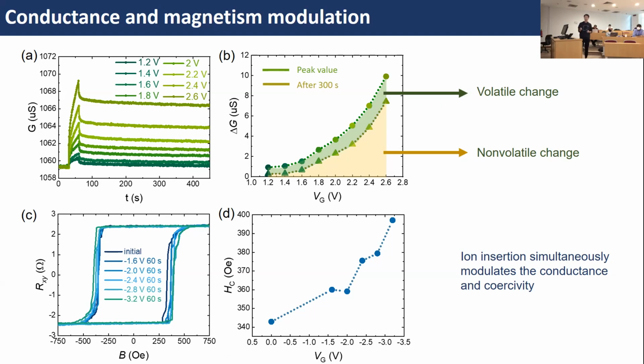Besides that, we also noticed that the ions trapped in the films can also tune the coercivity of this film, because the Co/Pt films show a PMA structure. And then by applying continuous negative gate voltages, we found that the coercivity is gradually increased.